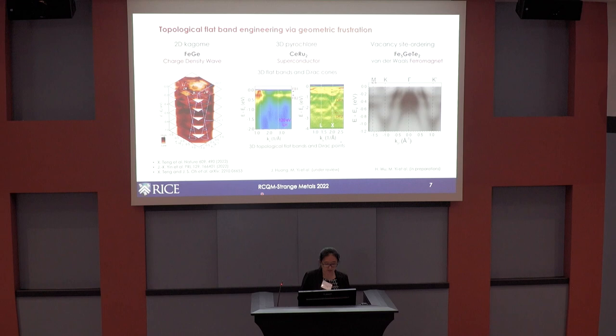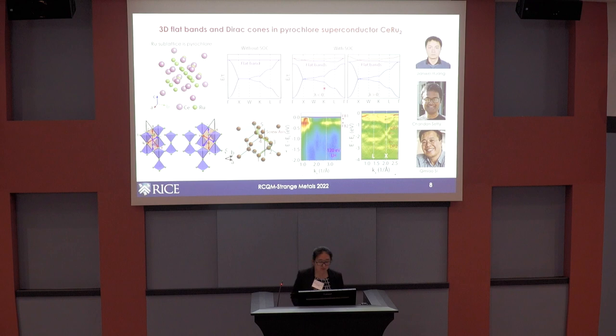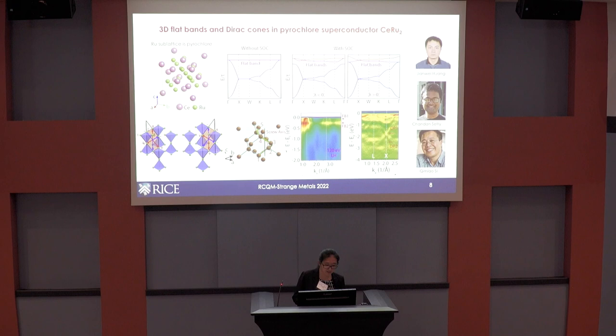I want to introduce our recent work on three-dimensional pyrochlore lattices. In the structure of a pyrochlore lattice, if you cut through it, you can expose a Kagome lattice. Importantly, the destructive interference is actually three-dimensional. In a unit cell of four lattice sites, the site not belonging to the Kagome lattice has exactly zero amplitude. This means the Kagome layers in the pyrochlore lattice are completely decoupled from each other — an improvement over 2D Kagome systems where interlayer coupling always exists in bulk materials.